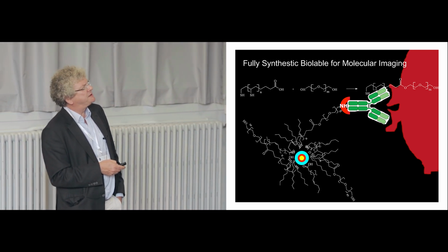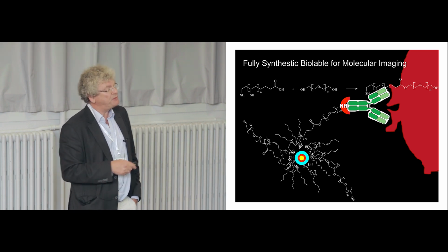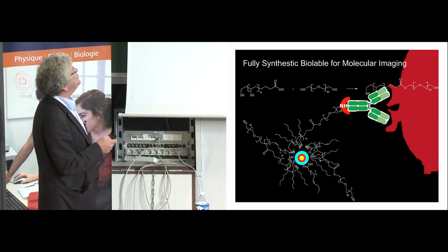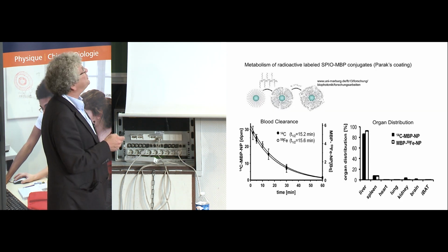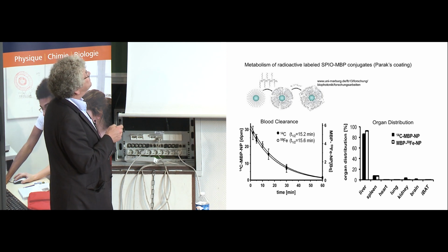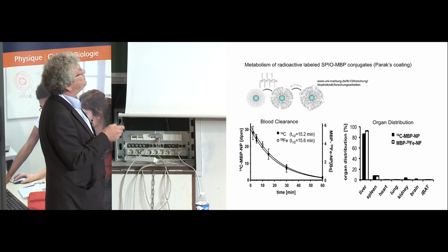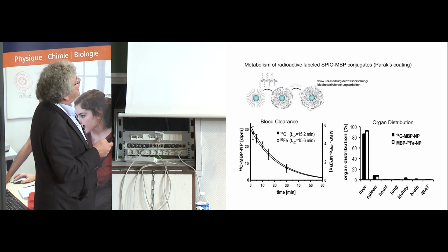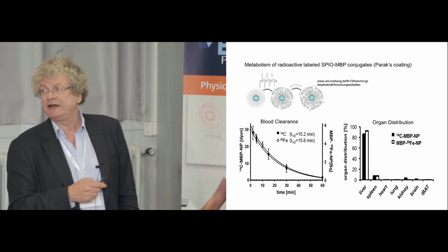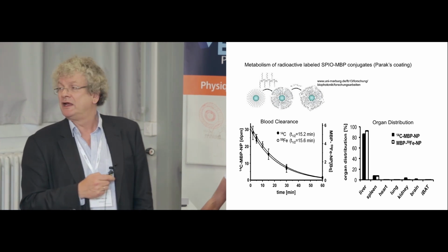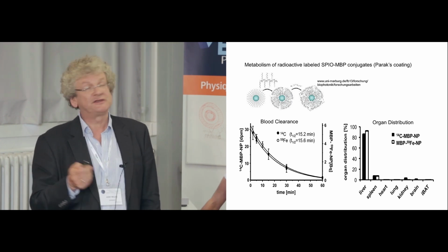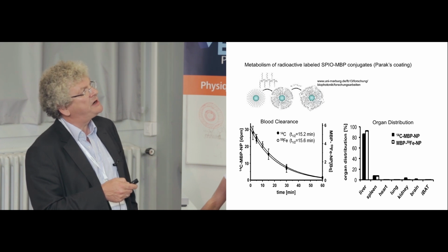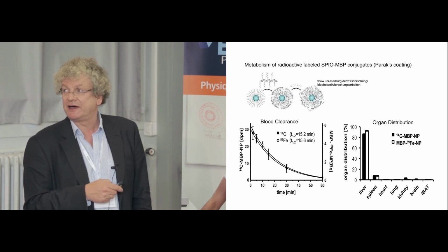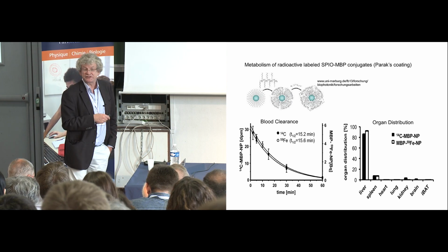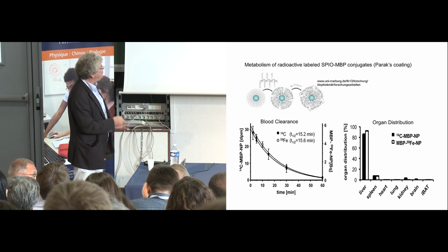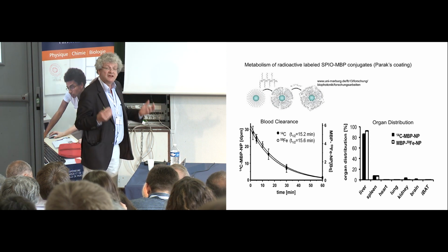Now, we started with a coating which is similar to what I told you there, slightly a little bit different. That is what Parak's group developed. So where these side chains interact with these top topo ligands and then form a PEG shell around the particles. And what you see here is a measurement of blood clearance of these type of particles where iron oxide particles were incorporated. You can do the same with quantum dots, of course, also. And they looked here in radioactive labeling experiments for blood clearance times. And here the blood clearance time is something like 10 minutes, not much. And within something like an hour, everything is delivered into the liver.